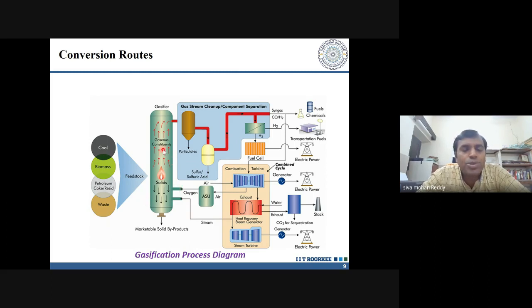As soon as you do it, most of the carbon material is going to be completely gasified, and you have a very small quantity of solids, which are collected at the bottom. Whatever product comes out from the gasifier is fed to a cyclone separator, where you can remove the gas and the solid particulate matter. If you have any sulfur acid gases present over here, you are going to remove those acid gases and clean it up, leaving the remaining gases like carbon monoxide and hydrogen. Some is fed to the syngas, where you can synthesize fuels and chemicals, and part of the hydrogen that is generated can be directly used as a transportation fuel, or to generate energy via the fuel cell, or from direct combustion, right?